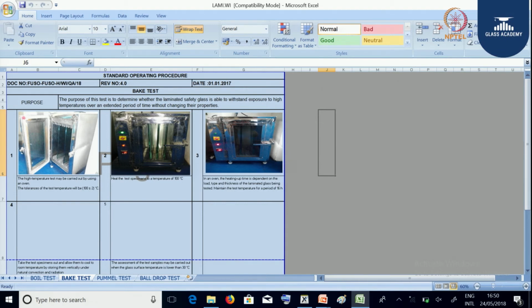Then gradually, every 1 hour we are going to increase the temperature by 10 degrees. For example, if I am keeping the glass at 100 degrees centigrade for 16 hours, on the 17th hour I will be keeping 110 degrees centigrade, on the 18th hour I will be keeping 120 degrees centigrade. Like that, every hour I am going to increase the temperature by 10 degrees, and I will be taking out the glass, inspecting it for bubbles or any discoloration, and again placing it back in the oven. At a particular temperature the bubbles start to form, I will be noting the temperature.